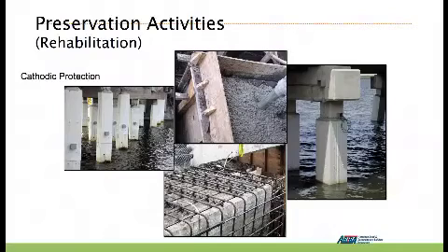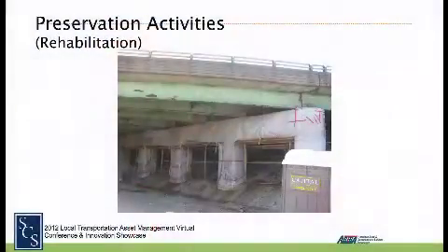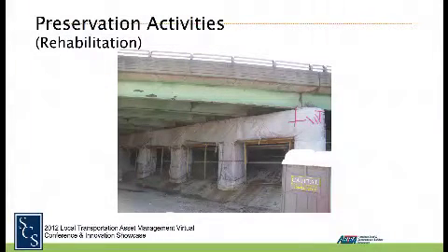What it does is put out a small amount of current to counteract the corrosion current so that you are preserving your structure. That is an example of what Florida is doing on a lot of their structures because a lot of them are in seawater. And here's an example of where you can pull out the salt that's already gotten into your structure using a technique called electrochemical chloride extraction, where you're actually positively charging a metal and your negatively charged chloride ion is pulled towards the positively charged metal. So that's what you're doing in this particular structure here. It may take 90 days and that's it. When you're finished, you seal the surface and you move on.